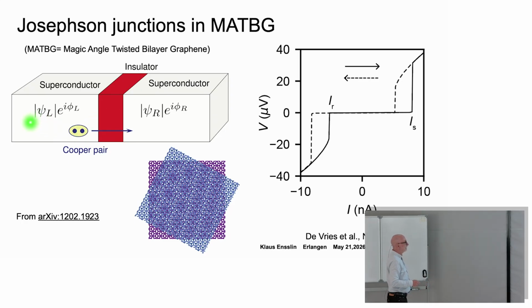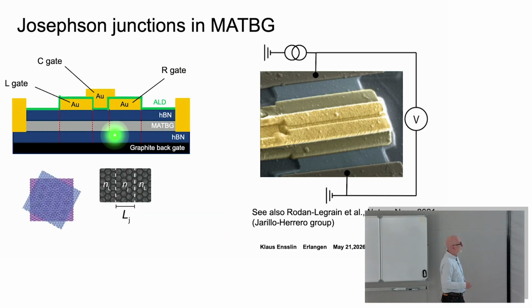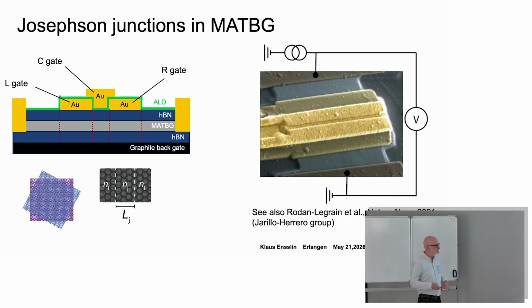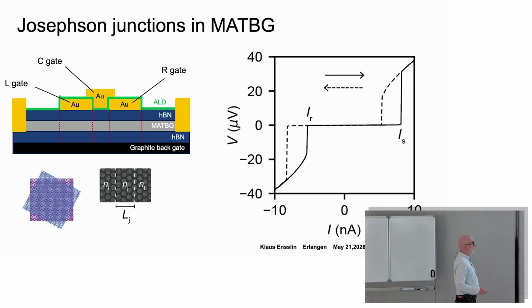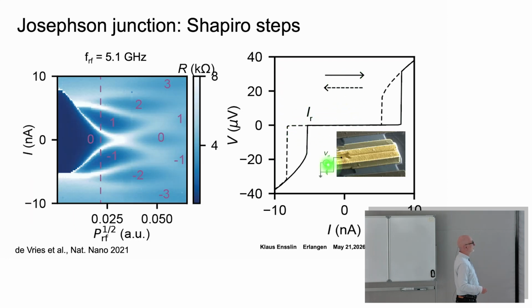And what we have done is we have taken such a system and we built a Josephson junction. And this is well known for standard systems, taking aluminum oxide, and so forth. But we can do the same thing by gating. So here's our twisted magic angle graphene. We have gates here. We can induce superconductivity in the leads, and then we have a center gate to create an insulating barrier, because you can switch between superconductivity and not just simply by gate voltages. And if you do that, you find a very nice Josephson junction behavior. You can apply high frequencies, and you see very nice Shapiro steps. So if you look in the textbooks, this looks very similar to what has been done in aluminum and aluminum oxide.